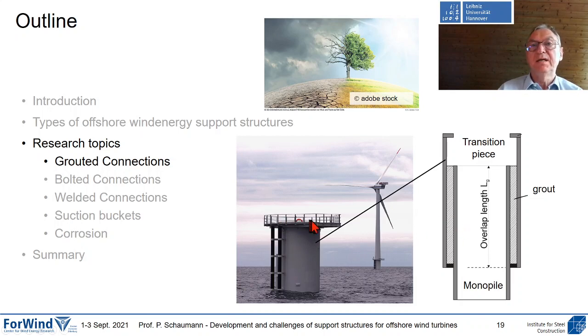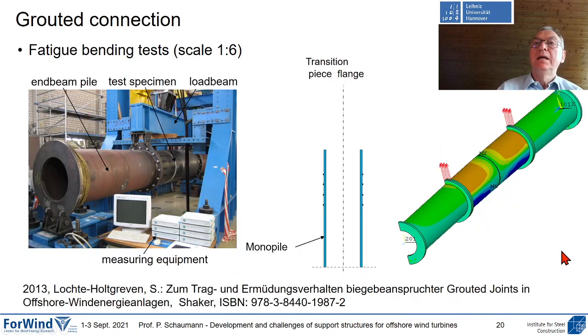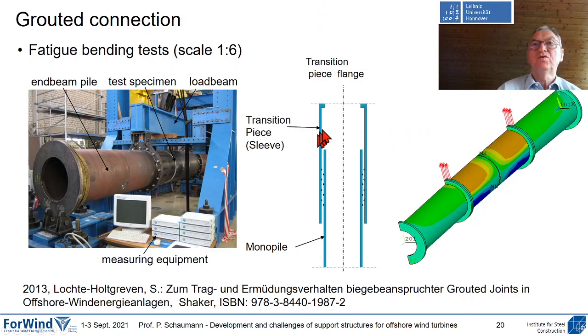So, and what we see here is the transition piece. We have this transition piece connected to the monopile with this grouted connection. And we started our investigations with fatigue tests on these grouted connections. We see here the grouted connections, to improve that, to decrease the overlap lengths. And we see here in the middle again how this works. The grouted connection, we have transition piece and the monopile connected via this grout connection.